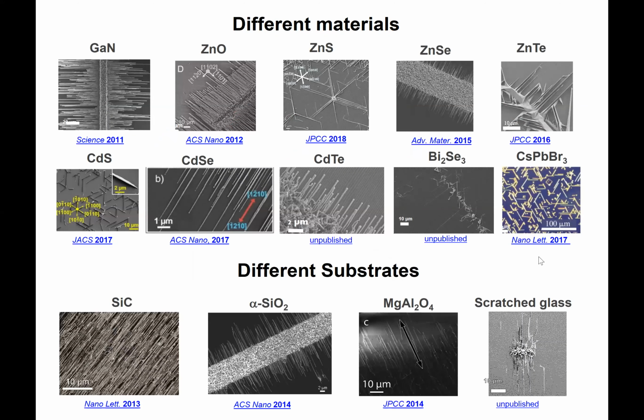We have been using this approach with many different materials like gallium nitride, zinc oxide, sulfide, selenide, telluride, cadmium sulfide, selenide, telluride, bismuth selenide, which all grow by the VLS mechanism.